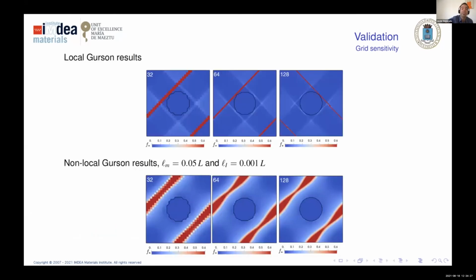And if we go to the microfields, we can see very clearly the difference. In the case of local Gurson, bands become smaller and smaller, but in the case of non-local Gurson, the size of the bands is independent of the voxel dimension, of the discretization. And what we observe here, this thinning of the damaged band, is due to the boundary condition between the phases. So we have a free Neumann here. Because we don't want to introduce damage in the non-damaging parts, the distribution of the damage is affected by this. This is something that will happen also in phase field damage, and it comes from the free Neumann boundary condition.